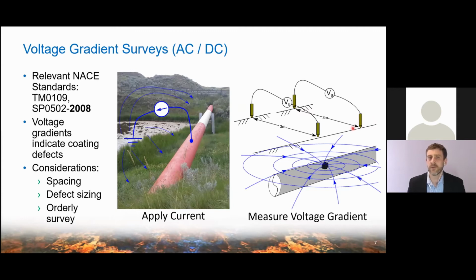So we walk above the pipeline, and basically what we do is we measure the voltage right above the pipeline to a location offset, say 3 meters away. And that voltage difference is picking up the voltage gradient associated with that coating defect.